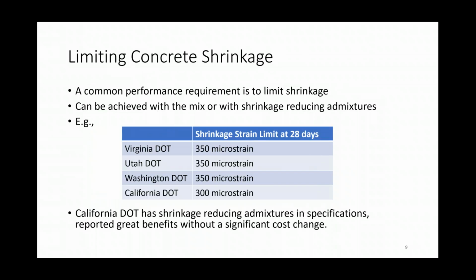Okay, so the second thing to say about concrete mix was that limiting concrete shrinkage strains seems to have a big impact. That's really a common performance requirement we saw when people had these high performance mixes. And some DOTs in the scan achieve it with shrinkage reducing admixtures. California is a big fan of this, and they reported greatly benefiting from shrinkage reducing admixtures without really increasing the costs all that much.